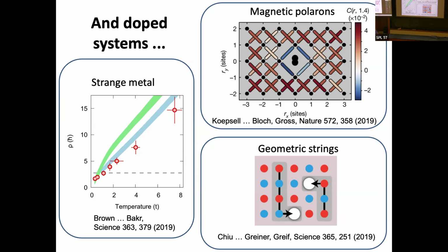And a lot of the interesting physics of the cuprates has to do with the interplay of spin and charge degrees of freedom. And so here the physics that was studied was you can look at the transport of the hole in the antiferromagnet. As you can imagine, as the hole moves around, it disturbs the antiferromagnet. And so what you could do microscopically is you can find a dopant in these snapshots that you introduced, and then evaluate the spin correlations around it. And you can look at the local disturbance of the spin correlations around a hole dopant, for example.